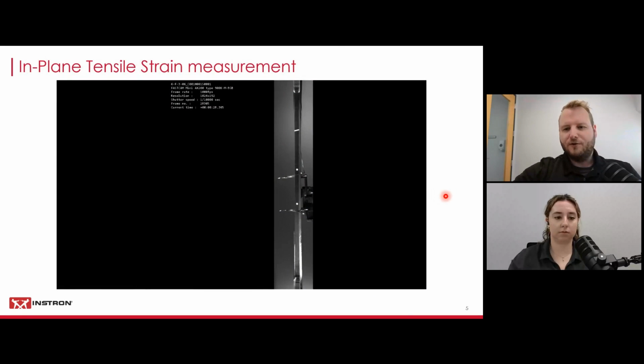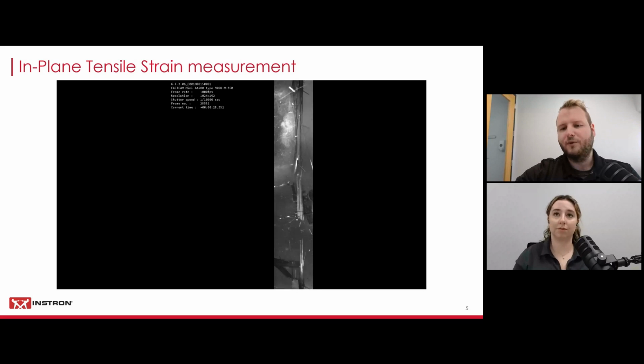Now, to show you some of those challenges when testing these materials, we would like to show you a video that demonstrates some of them. There's certainly a lot of them that we're facing when we're testing carbon fiber reinforced plastics. This video was recorded at 10,000 frames per second. We have a carbon fiber specimen, which is very, very stiff compared to traditional materials, and even recorded at 10,000 frames per second, the break really happens instantaneously, and the whole material really kind of explodes on you.